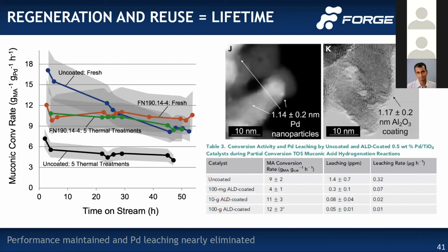So here is some of the data, for the regeneration and reuse of the catalyst. That blue decreasing data is a fresh catalyst without an overcoat. And here is no overcoat after 5 thermal treatments or regenerations. So you have a significant drop in that conversion, or productivity of the catalyst, over time after you regenerate it. These blue, green and orange lines are a fresh catalyst with an overcoat, and after those same 5 thermal treatments, you have the same conversion over time.